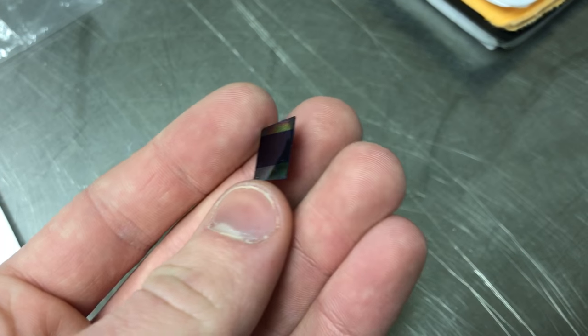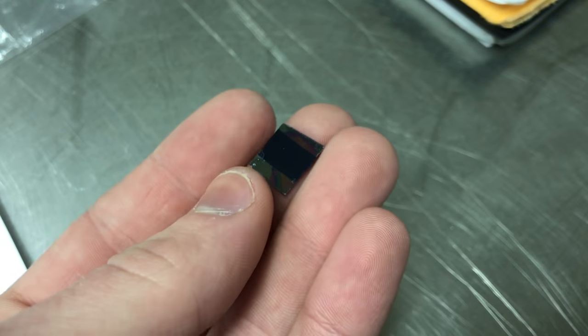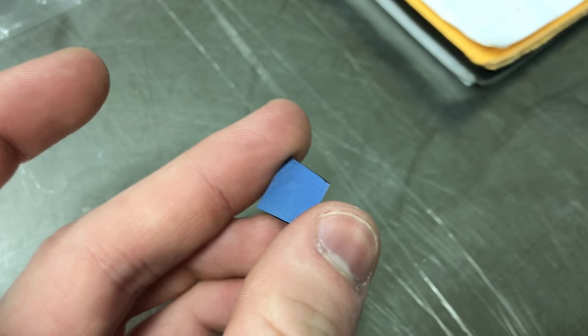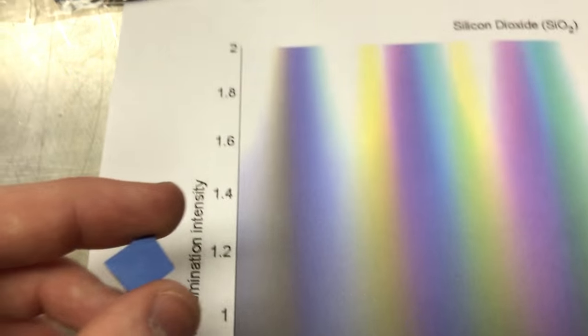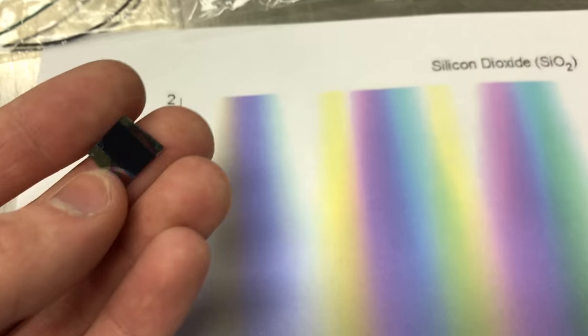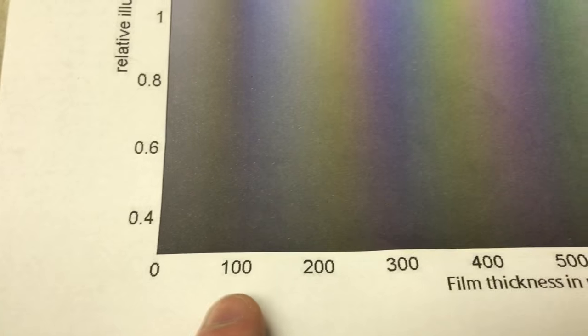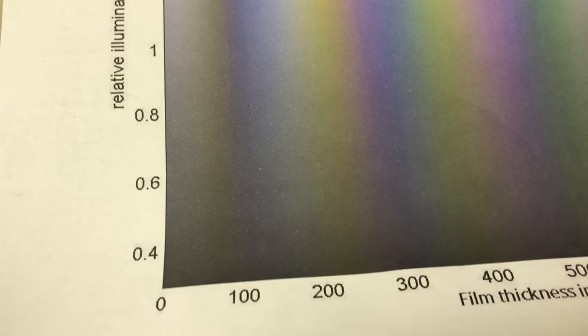Looks like I actually overshot the gate dielectric layer that we were shooting for. I flipped to the back of the wafer just so you can see the color easier because it's unpolished. So that's the shade of blue. So that puts us right here on the color chart, which is just above 1,000 angstroms. And we were going for about 500 to 600 angstroms. So I checked my furnace and I actually left it on too hot and it went up to 1,400 degrees C. And that's where oxidation happened a lot faster than we wanted. So that's going to mean that the threshold voltage to turn this device on is going to be much higher than I originally wanted it to be. Because, you know, this region here for a gate oxide is very, very thick. We'll see how it works.